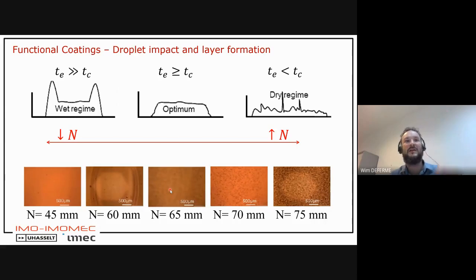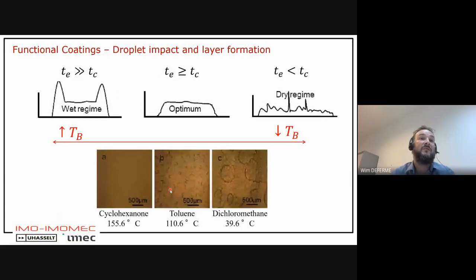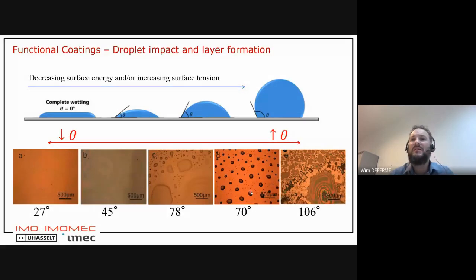So this is the influence of the height of the nozzle. You also have the influence of the temperature of the solvents that you use. You can use a high boiling solvent, cyclohexanone, for example, or dichloromethane and so on. So this also plays a role on the evaporation and the final layer formation. So you always have to think about not only temperature and distance and so on, but also using optimal ink formulations to achieve nice results, nice layers.